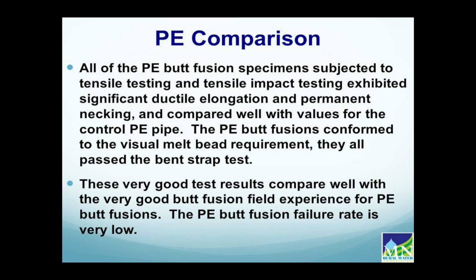So how do these field failures compare to the laboratory data? As far as polyethylene, all of the PE butt fusion specimens subjected to tensile and tensile impact testing exhibited significant ductile elongation, necking, and compared well with values for the control pipe. That's the key—comparing the butt fusion to the control pipe. The polyethylene butt fusions conform to the melt bead requirement, and they all passed the bent strap test. These are very good laboratory results, and they compare very well with the very good butt fusion field experience for polyethylene, which has been used over 50 years extensively in the natural gas distribution industry, where we have to have leak-free joints.